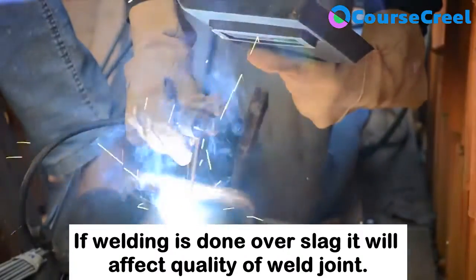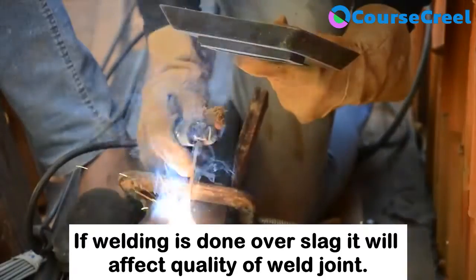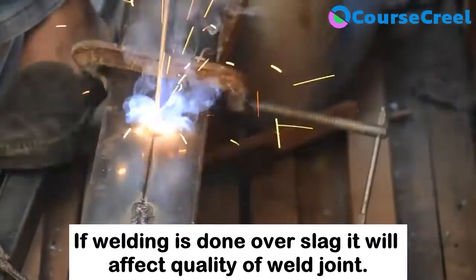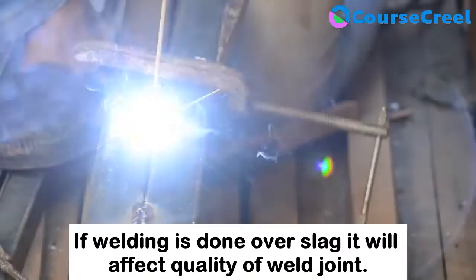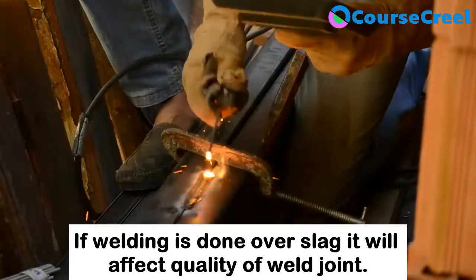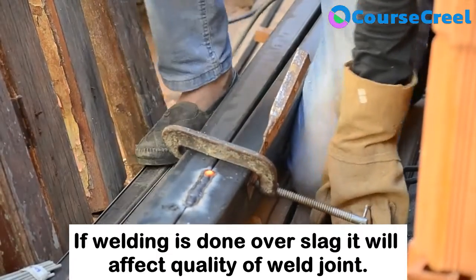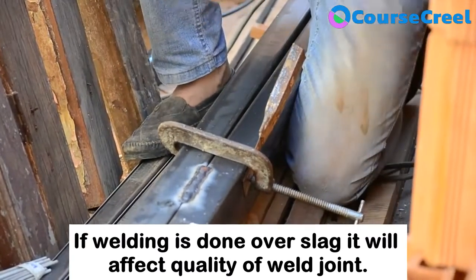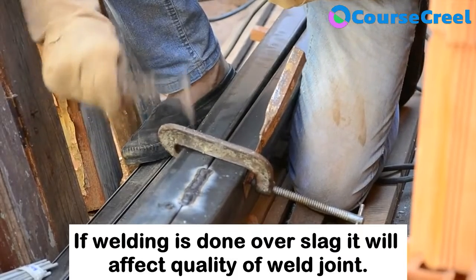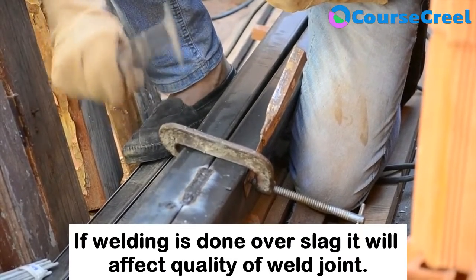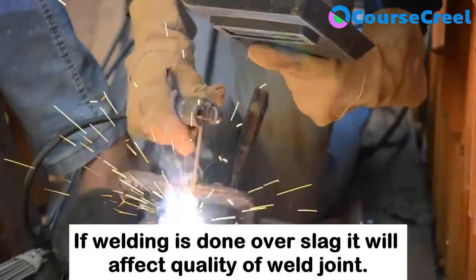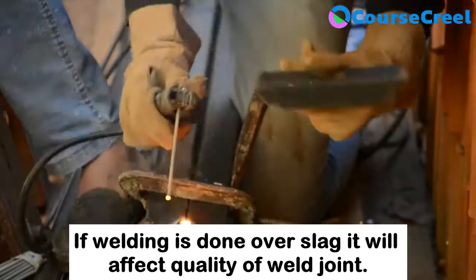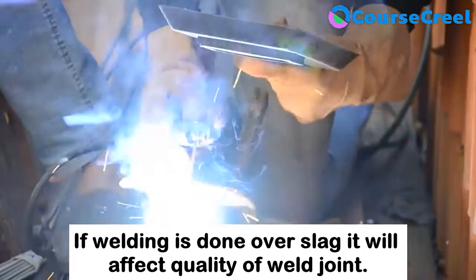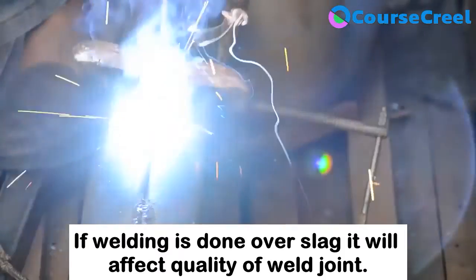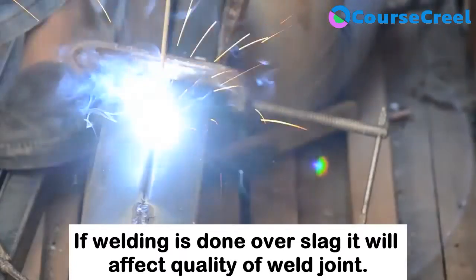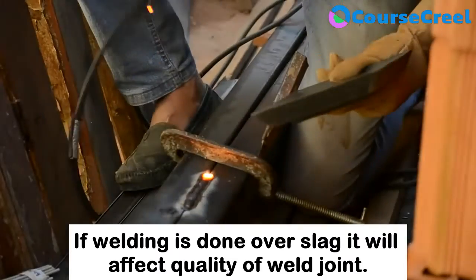In that case, what will happen if we are doing welding over slag? If we are doing a second run of welding over the layer of slag, what will happen? During the second layer of welding, the slag is going to come in contact with the heat. With the application of heat, the layer of slag will melt and remain under the weld puddle and it will contaminate the new weld. The slag will get burned during the welding and it will affect the quality of the weld joint. So if we want a good quality weld, we need to remove the layer of slag anyhow to get a good quality weld joint.